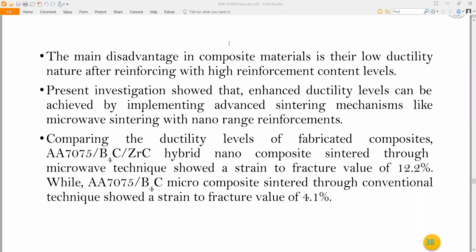Then the main disadvantage is composite material with their low ductility nature after reinforcing with high reinforcement content levels. Present investigation showed that enhanced ductility levels can be achieved by implementing advanced sintering mechanisms like microwave sintering with nano-range reinforcements. Comparing the ductility levels of fabricated composites, AA7075 B4C ZrC hybrid nanocomposite sintered through microwave technique showed strain to fracture value of 12.2%, while AA7075 B4C microcomposite sintered through conventional technique showed a strain to fracture value of 4.1%. So we are getting a large difference. In one place it is 12.2% and in the other it is only 4.1%.